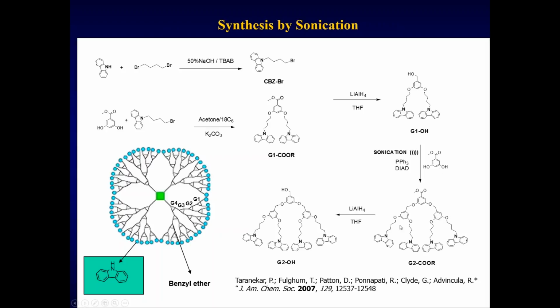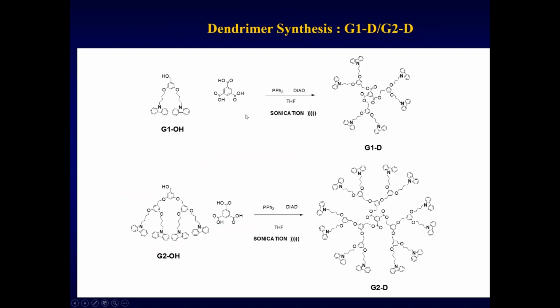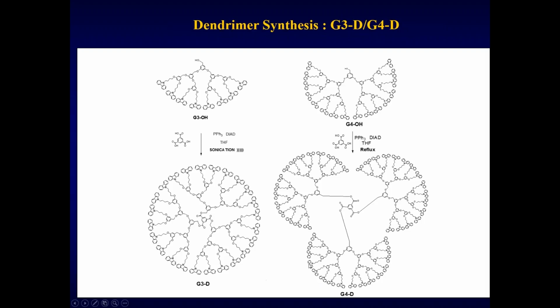And this was actually done very efficiently using a sonication reaction. Again, by reduction of this, we are able to convert this into another AB2 type monomer to produce G2OH. So using these different dendrons, we were able to assemble dendrimers with a trifunctional core to produce your G1 dendrimer, G2 dendrimer, and then even bigger dendrimers such as G3 and G4. These are what we call reactive or electrochemically active dendrimers that can be utilized like the terthiophene dendrimer for certain devices.